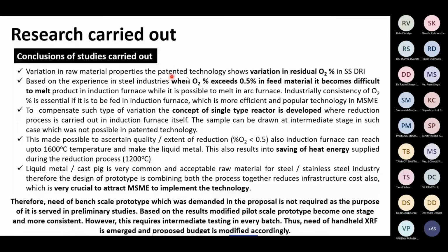Based on the experience in the steel industry, when O2 exceeds 0.5% in the feed material, it becomes difficult to melt. We observed this, so we also recommended to the steel industry that they reduce this oxygen content, so that the oxide layer on the steel can be reduced, and further there is less generation of the 3Ss, that is sludge, slag, and mill scale. We are trying to develop this single type reactor, which is under process. The two-step process is already proven, but the single step process we are trying to prove.